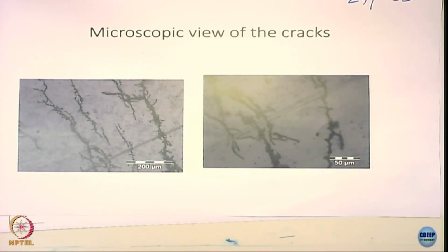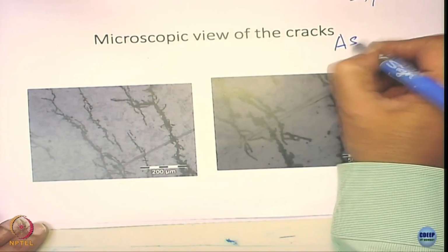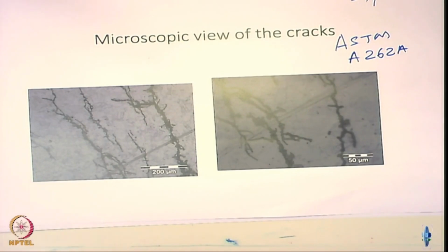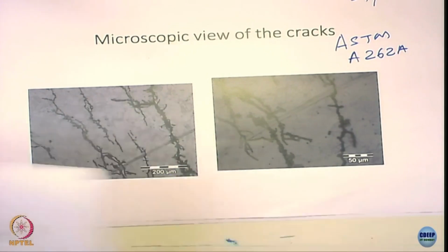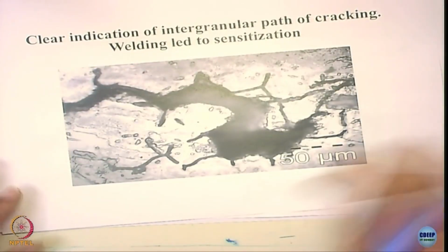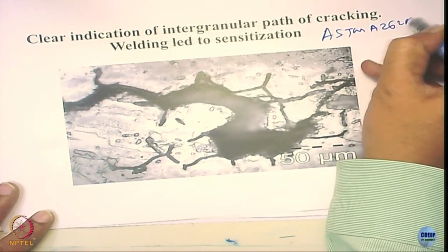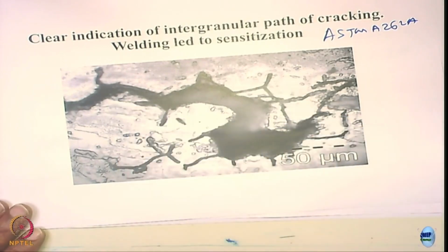If you find a crack like this, both of these were subjected to what you have already studied, sensitization, right. It is a stainless steel, and the ASTM A262A test was done. You do not see any sensitization here. You see the sensitization taking place here, right? Here also you have the ASTM A262A test, but there is also sensitization taking place.